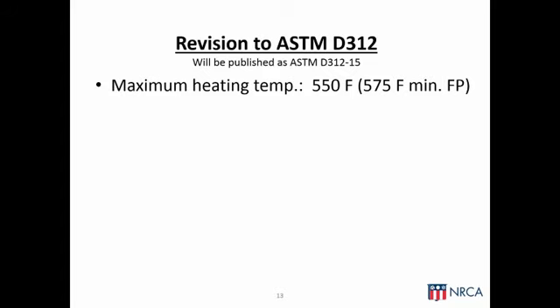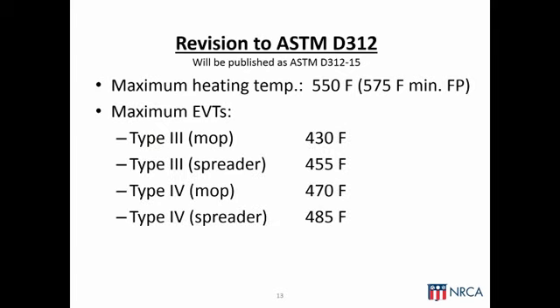So that is one of the means we're using to address some of the health and safety issues associated with asphalt. Also, for the first time, the ASTM standard will reference or have specific maximum EVT values, in other words, point of application temperature values, and specific values are provided for both Type 3 and Type 4 asphalt and mop and mechanical spreader applications. You will notice these values are relatively significantly lower than what we are dealing with in the field currently. I think our average Type 3 asphalt